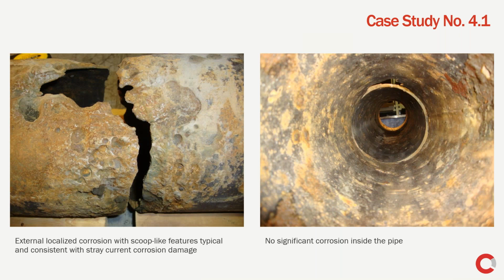This is another pipe that corroded due to stray current corrosion, and the features that are associated with this degradation mechanism are more visible here. The scoop-like features on the surface of the pipe are usually typical for stray current corrosion damage.